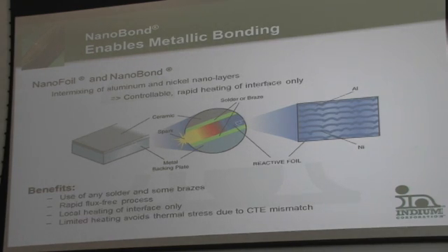And one of the key advantages is that it allows metallic bonding, and I'll talk about some of the applications in a minute. So you form a so-called nano bond with this nanofoil material. We already talked about this. By applying solder, you can have a flux-free process, that is, without any organic materials. It's a local heating. That is, you don't have to heat up, for example, if you're bonding together two very large, heavy types of materials.